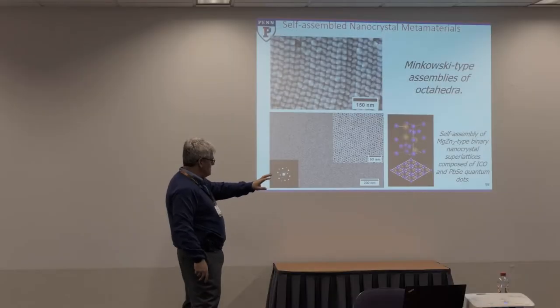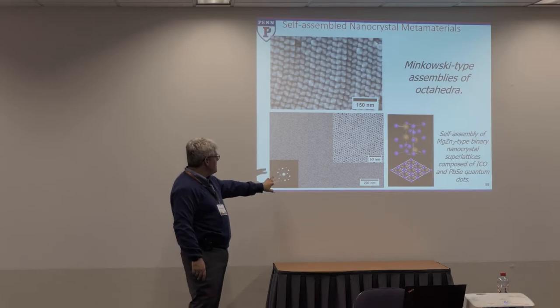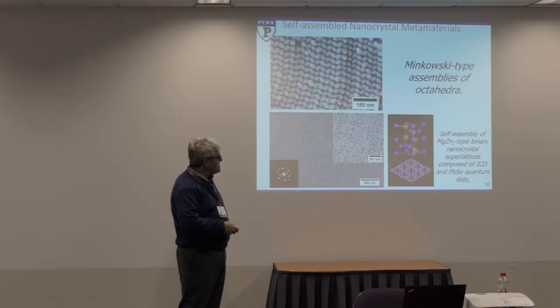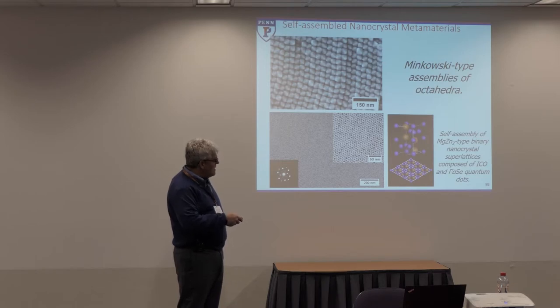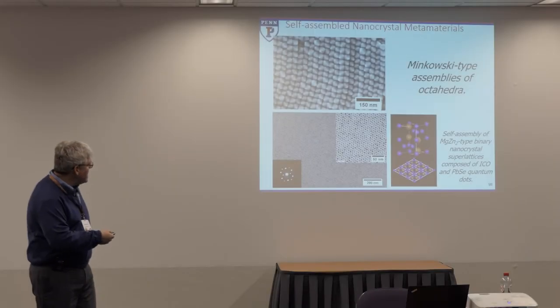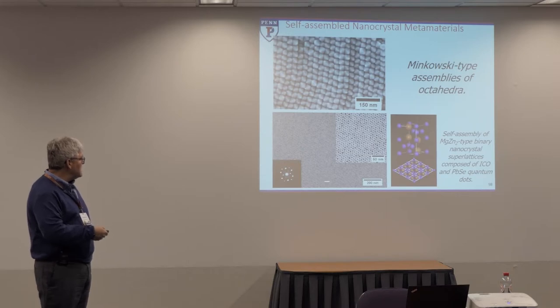All right, so, maybe to motivate, I'll just give this example. We did talk about semiconductor materials. We talked about plasmonics. Just as a motivational piece, this system is two different types of particles that are assembled together. One is a doped oxide with a resonance at about 1.5 microns that comes from the plasmonic interaction. And this other system is a quantum dot that has an absorptive interaction at about 1.5 microns. These are some of our first efforts to see whether we can begin to use the strategy of pairing up local electrical field increases due to the antenna effect with quantum emitters that are tuned to have a synergistic interaction. But in this case, they're now tiled. Rather than being individual structures, they're assembled into an extended 3D crystal structure.